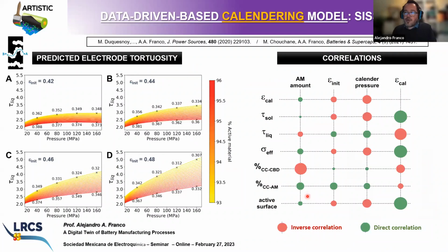And here I'm going to show you an example, right, of what you can get with this technique. You can predict the influence of calendering pressure, the initial porosity of the electrode, and the formulation of the electrode, okay, each curve here with a different color corresponds to a different formulation, on the tortuosity factor that you will get in your electrode upon calendering. You see that when you increase the calendering pressure, the tortuosity factor increases in these four cases. This is expected because the electrode is becoming more and more compact, the pore network is becoming more and more tortuous. But the nice thing with this method is that you can quantify the degree of impact.